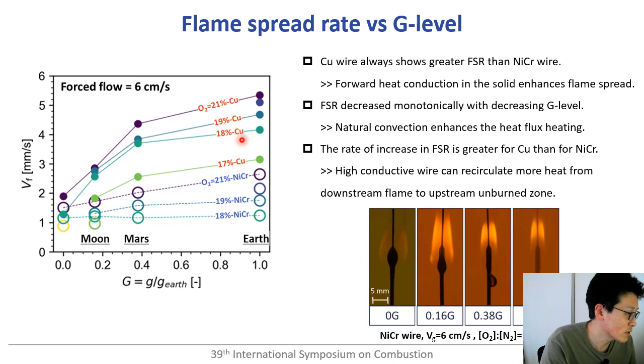And as for the effect of gravity, spread rate decreased monotonically with decreasing gravity level for both copper and nichrome wires. So this would be attributed to the change of heat flux heating due to the change of natural convection. As I showed in the video, flame size changes at different gravity levels. So this could be one of the reasons for the enhancement of flame spread in the higher gravity condition.